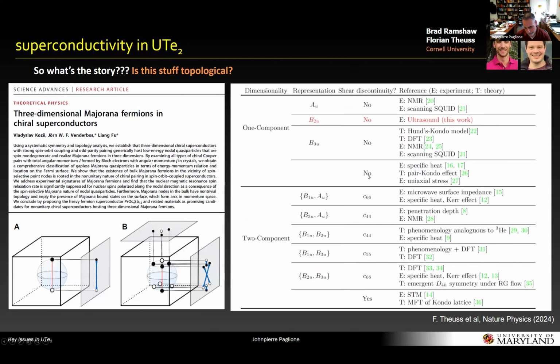Okay, so finally, is this a topological superconductor? Well, it probably depends on who you talk to, even theoretically. But what I believe certainly is that it's a point node superconductor, and it's of the B3u variety. That implies that there are likely some projected surface states. And this has some implications for some of the experiments I went through, in particular penetration depth and NMR experiments, as well as other surface sensitive experiments.